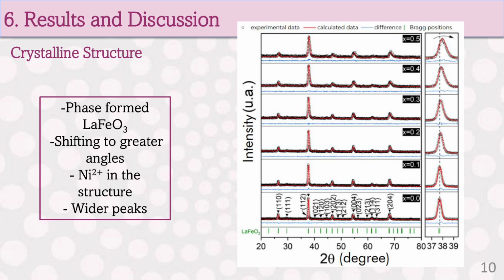In all LaFe1-xNixO3 patterns with x up to 0.5, the main diffraction peak is seen between 37 and 38 degrees, whereas the dopant concentration increases, this peak shifts towards higher values of 2 theta, indicating a decrease in the interplanar distance, i.e., there is a higher concentration of atoms in the unit cells, which is a consequence of the difference in ionic radius between Fe3+, 0.645 Å, and Ni2+, 0.69 Å. An increase in peak width is also observed, which is attributed to a loss of crystallinity in the material due to the dopant and its accommodation in the crystal structure.